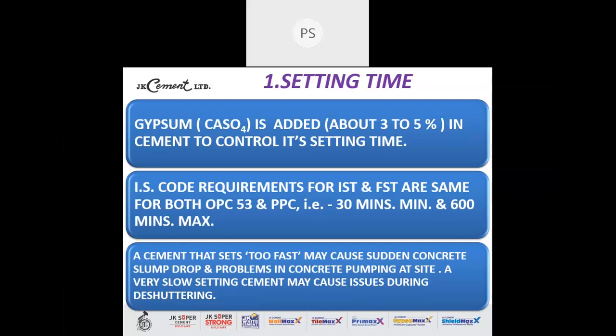So it takes a time of minimum 1.5 to 2 hours for a concrete mixer or the transit mixer to reach Dadar from Bandra to Dadar. In that time, the concrete should not set. At the same time, it should be pumpable when it reaches the site. So if the cement setting time is too fast, it will cause pumping issue and your pump will get choked. So quality control engineer needs to keep a check on it.